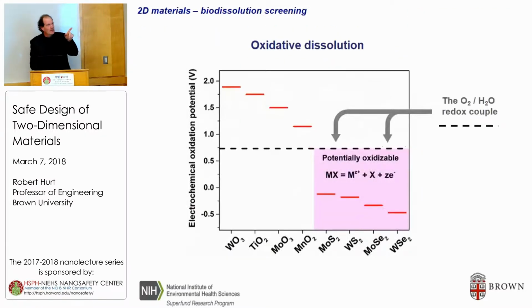But in fact, this is only one mode, simple non-redox dissolution. We also have oxidative dissolution. And many of our nanoparticles follow this paradigm: copper, silver, even nickel. And here you're plotting, this is a kind of an in silico screening method where you're plotting the oxidation potential of the material for this range of materials that we're looking at. And what you do, I can't explain this in detail, but you compare the oxidation potential of the material to a redox couple. And this is oxygen water, which is always present in our systems. And the ones that fall below that line are thermodynamically potentially oxidizable.